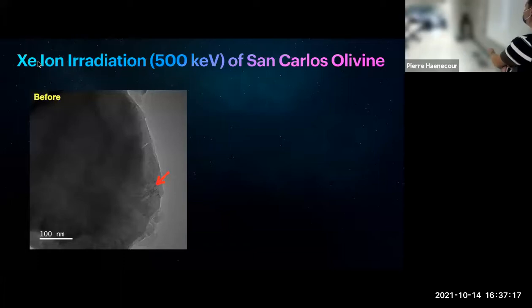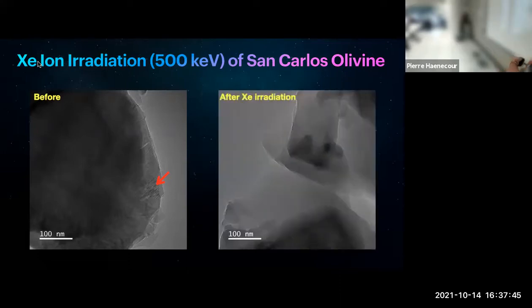Okay, so here I'm going to show you the transmission electron microscope image of the San Carlos olivine before the heating. If you're not familiar with TEM imaging, you can see the lattice fringes here on the olivine, basically showing that it's crystalline olivine. So it's a typical San Carlos olivine. There is nothing wrong in terms of the crystallinity of that particular olivine grain. It's just crystalline olivine, which is all we cared about at that stage.